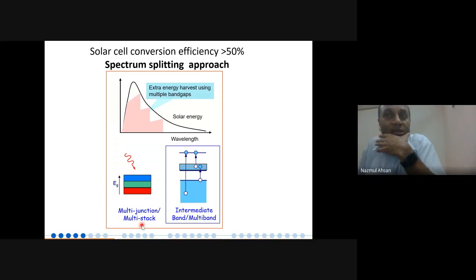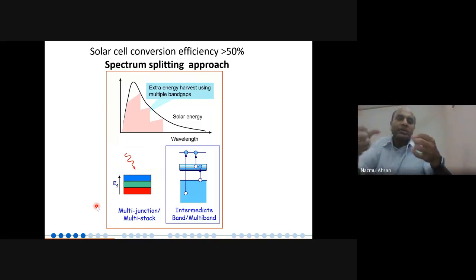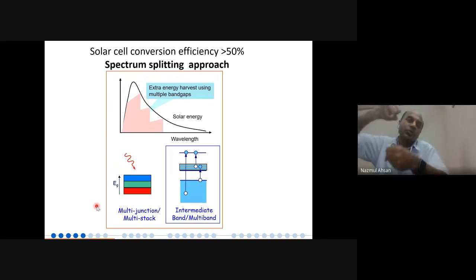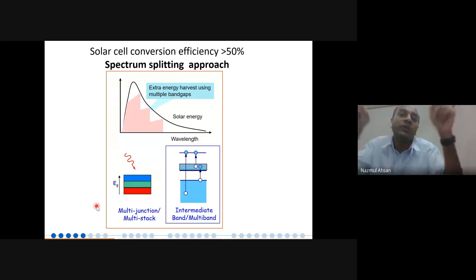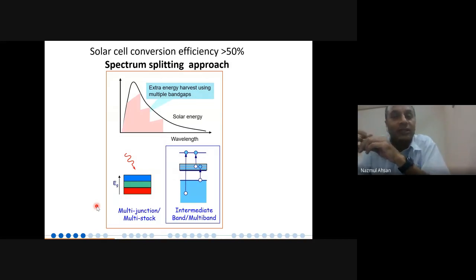It's not only the material. The most expensive part is the procedure. For example, we use molecular beam epitaxy for this kind of material, and it is very challenging to achieve lattice matching because different semiconductors have different band gaps and different lattice constants. If you put one material on top of another, at the interface they have strain. This strain changes the ordering and brings a lot of defects. Those defects reduce the open circuit voltage and the current because they work as traps and trap the carriers. So you have reduced photocurrent and reduced open circuit voltage. So it's not only about cost, it's also about technology.